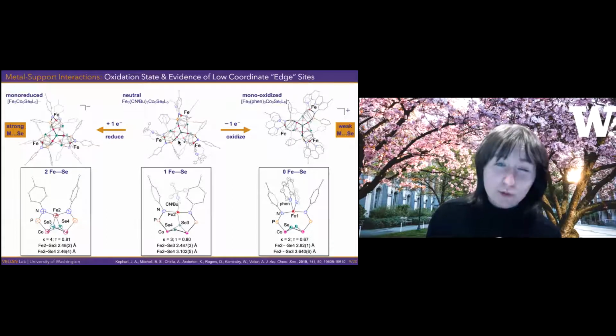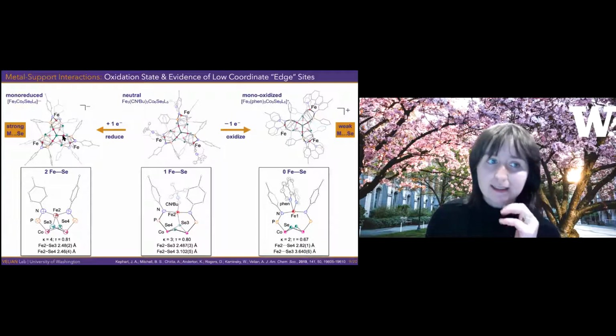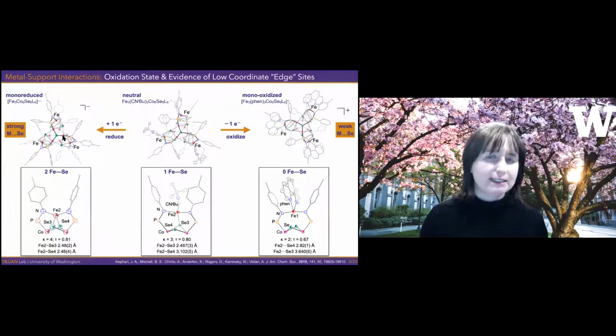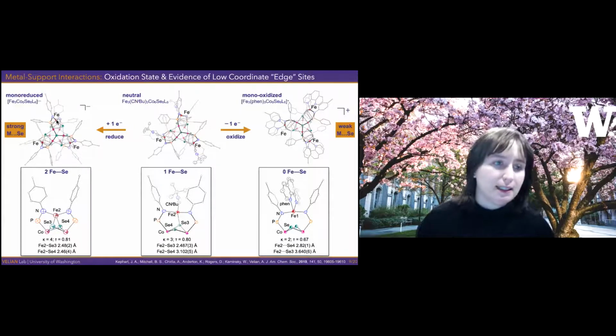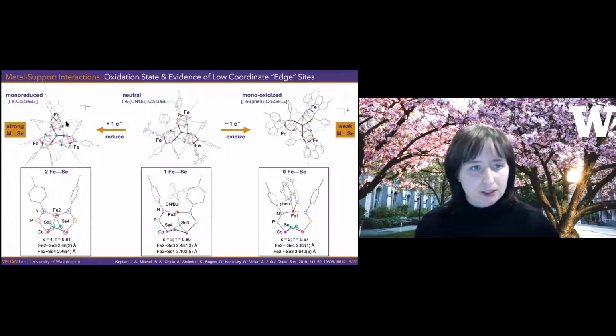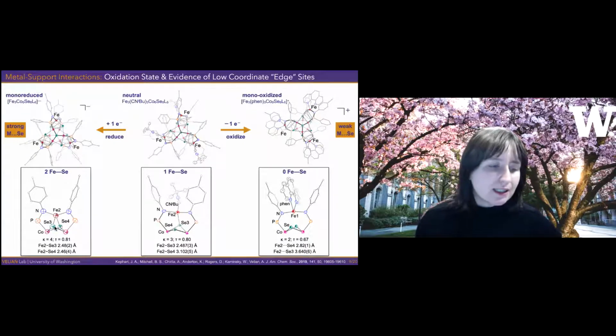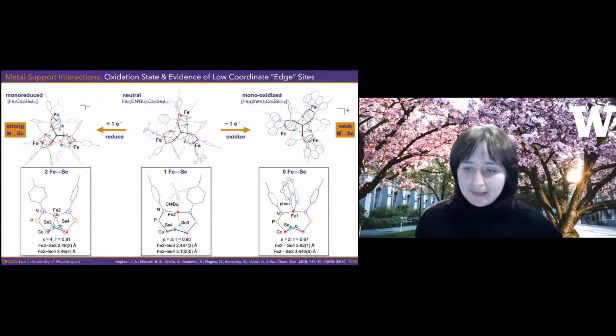But conversely, if you reduce the cluster, and again, we can isolate these, which is really helpful because you don't have to guess what exactly this compound is. We can cleanly produce and isolate the molecular species as monooxidized and monoreduced. And so in the reduced case, we see the opposite. Now the iron has no affinity for external ligands. Every ligand that we've exposed to this cluster no longer binds to the iron. The iron is just completely engaged with the 2 selenium. So we have 2 selenium-iron interactions, 1 and then 0, and that's switchable by this redox series.